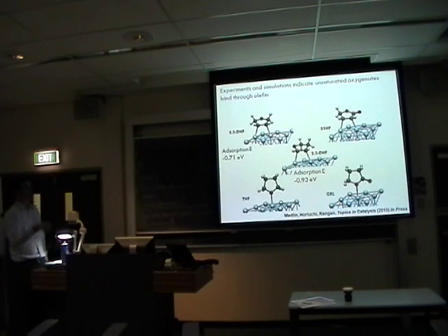And then furthermore, the proximity of the carbon-carbon double bond, I know it doesn't show up very well here, but here's the carbon-carbon double bond in the case of 2,5-DHF, and it's here in the case of 2,3-DHF. The proximity strongly affects how strongly adsorbed the molecule is, and that actually, although I didn't go through the story, affects what reaction products you see when you study the reaction of 2,3-DHF versus 2,5-DHF. Okay, and so by understanding these factors, we're able to link up the more complicated reactions of different kinds of sugar and carbohydrate derivatives in order to build up a picture of how different structural motifs affect reactivity.